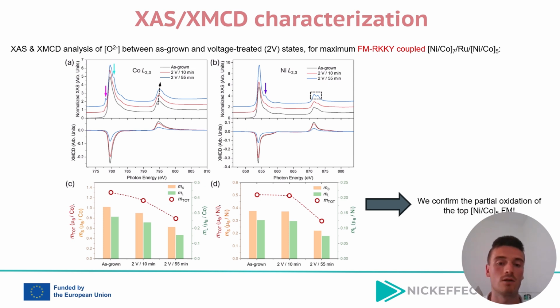Conversely, panels C and D quantify the spin-related, orbit-related, and total magnetic moments of the 3 different studied samples, showing a progressive reduction of these magnetic moments with increasing voltage treatment duration, which again is in line with the partial oxidation of both cobalt and nickel, as expected from the previous high-resolution analysis.